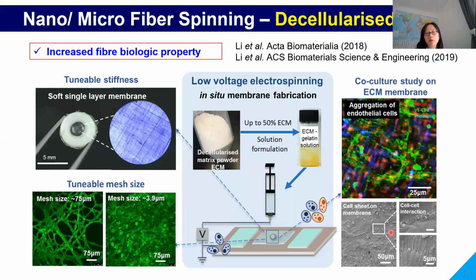The benefit of using solution fiber spinning is that potentially you can use a wide range of functional materials. A couple of examples shown here are our ability to enhance the fiber biologic property for supporting specialized cell growth, in this case, glomerular cells. The fibers are mixed with decellularized matrices and spun into fibers of different mesh size. And we can then guide the cellular behaviors by changing this material composition and also material morphology.